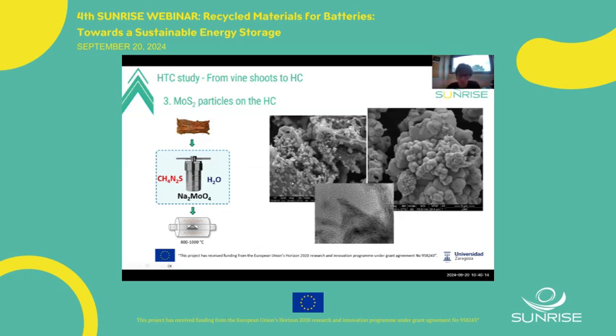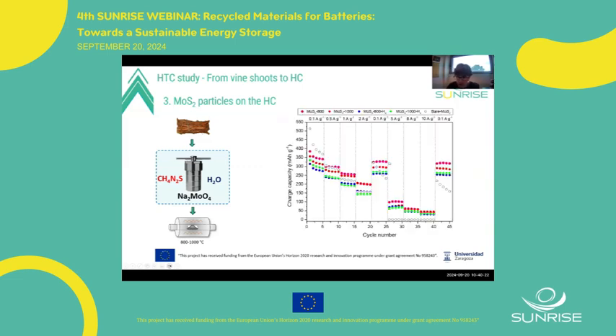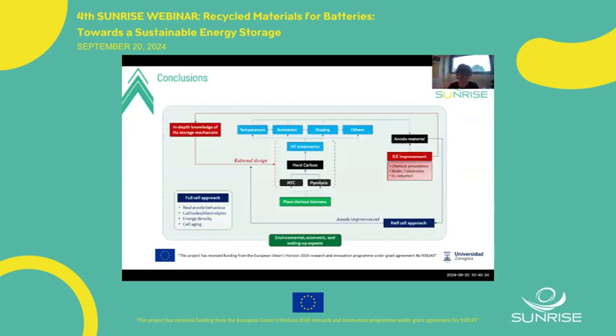As you can see here on the surface of the carbon, these kinds of spheres made of molybdenum disulfide appear. And when we checked the capacity, there were also improvements compared with other kinds of synthesis, for example, only with water or with pyrolysis.